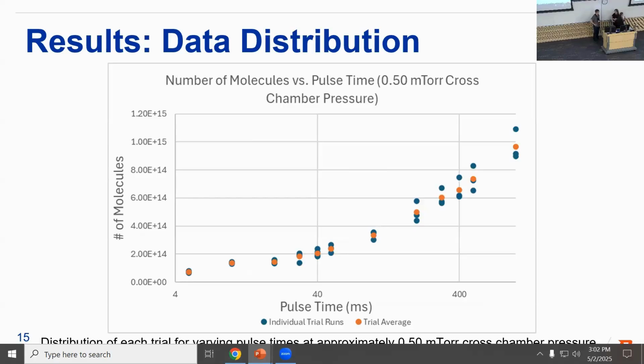Okay, so here you have an illustration of the distribution of the gas pulses by pulse time, specifically at a cross chamber pressure of 0.5 millitorr. The blue dots represent all the individual data points, and that orange dot there is the mean of the data set, so that you can see the distribution.